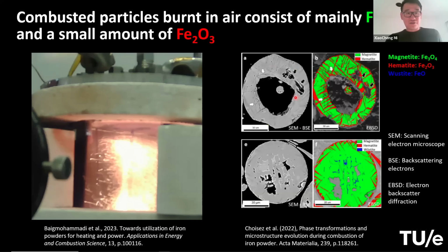In our theory right now, I think it will always be there in some particles, because in liquid phase, basically you can oxidize it beyond the stoichiometry of Fe3O4. And after you solidify it, it can only form the oxide or stay in the lattice form of Fe3O4. So that means there is more oxygen in your solidified particle than the lattice of magnetite can hold. And this oxygen has to go somewhere, right? There's a gasification process right upon the freezing of the particle. So we think that the reason we see this large cavity is due to this phenomenon.